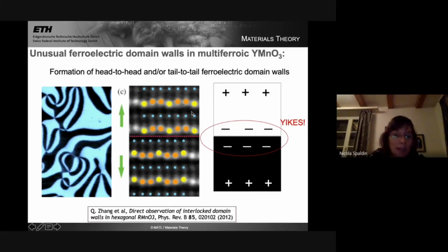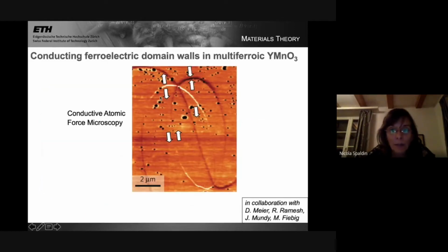And for the opposite case, if we went down between the black and the white, then it would have to bring in negative charges. It would have to bring in some electrons to screen the diverging electrostatic potential. And this is what it does. So this is now data in collaboration with a group of Dennis Meier, who's now in Trondheim, taken using a technique called conductive atomic force microscopy, which lets you see the presence of charge carriers. So it scans the surface again with a tip and measures the conductivity below the tip.